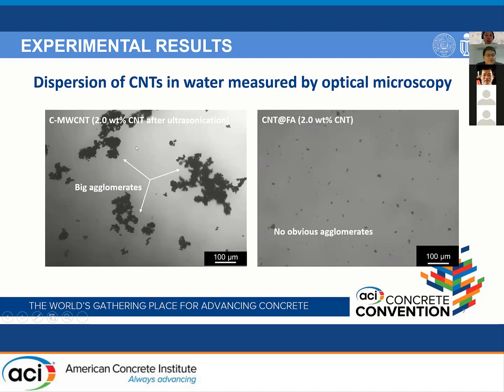And then we detected the dispersion of these two types of carbon nanotubes in water by optical microscopy. The dispersion results are shown in these two figures. The left figure shows the dispersion result of the commercial carbon nanotubes. From this figure, we can see that after ultrasonication, commercial carbon nanotubes tend to agglomerate together, and several big agglomerates can be observed in the suspension. This result suggests that the commercial carbon nanotubes are very difficult to disperse well in water only by ultrasonication.